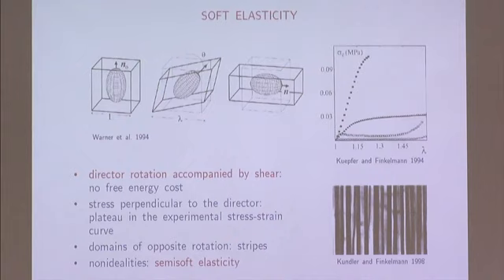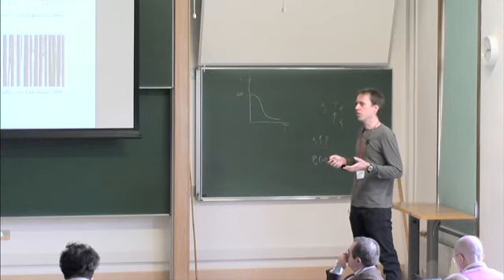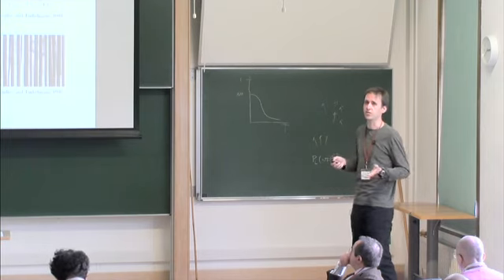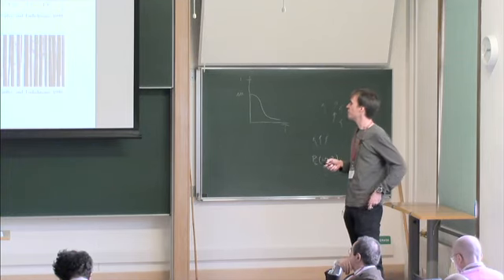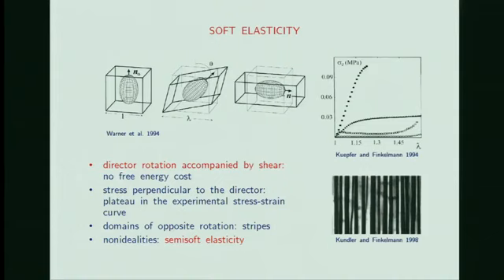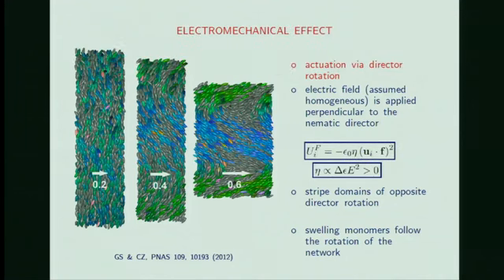So of course we were tempted to perform this kind of experiment also in our simulations, but for some technical reason it was not possible to do it by applying mechanical stress perpendicular to the director. However, one can invoke director rotation also by other types of fields, for example, by an external electric field. This has been done experimentally, for example, by Kenji Urayama, who studied the so-called electromechanical effect. So now we have our sample, again aligned along the z-axis, and then we apply an electric field perpendicular to the director, and above some threshold, the mesogenic units will rotate. The director will rotate towards the orientation of the external electric field.